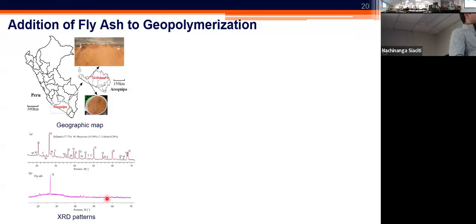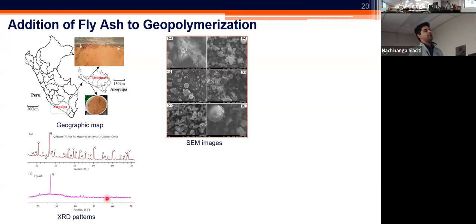So one example of the additional waste is the use of fly ash. Fly ash is a rich material in terms of the aluminum and silicon species that are a lot more reactive. You can think of the tailings generally as being unreactive or less reactive compared to something like the fly ash, which has a lot higher amorphicity and less crystalline structure, as you can see from the XRD pattern. So by simple mixing of the solid content of the mine tailings and the fly ash and repeating the process, you would have an opportunity to produce new geopolymers that hopefully would have some improved performance and characteristics compared to the tailing-only based geopolymers.